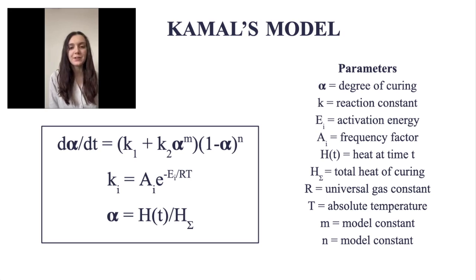The most accurate model for studying epoxy curing reactions is Kamal's model. This differential equation allowed us to determine the degree of curing, alpha, as a function of time. The reaction constants were calculated using the activation energy and frequency factor, which are known epoxy parameters. The total heat associated with curing is also a known parameter. And with the knowledge of the degree of curing from Kamal's model, we were also able to calculate the heat released at any given time throughout the reaction.